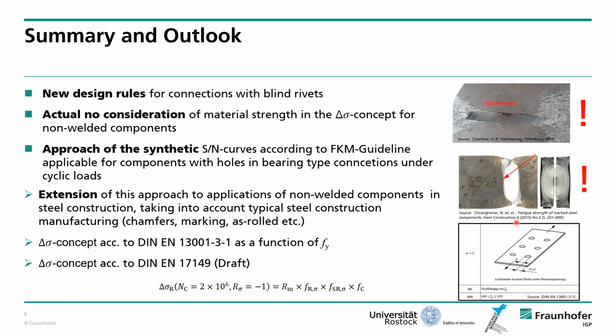For example, we have such marks on the components which directly influence the fatigue resistance, and furthermore, the delta sigma concept should be retained. And below you can see two standards which already have the delta sigma concept in their approach. The first standard defines the fatigue resistance of non-welded components as a function of the yield strength of the used material. And the second one takes into account several influencing variables in the verification of the fatigue strength, as you can see here in this equation.